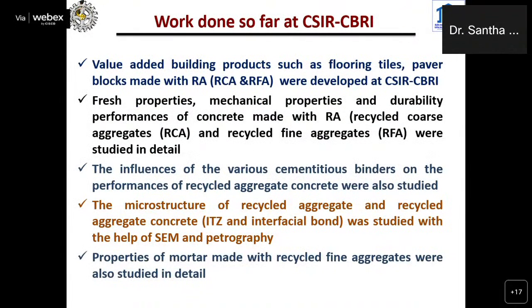So keeping these aspects in mind, we have focused particularly on various value-added building products such as flooring tiles and paver blocks that we have developed at CBRI. I will come later to how those building products meet the requirements of the specific IS standards. Then we have developed various grades of concrete from M20 to M45, and we have studied the fresh properties and mechanical properties using both 100% recycled coarse aggregate and recycled fine aggregates, and those performances were studied in detail.